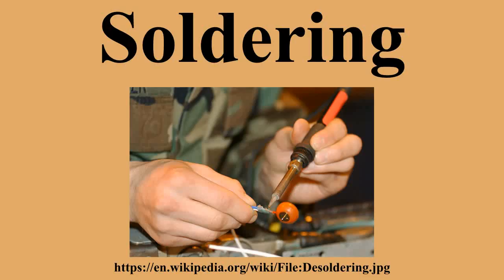These fluxes are called no-clean because the residue left after the solder operation is non-conductive and won't cause electrical shorts. Nevertheless, they leave a plainly visible white residue that resembles diluted bird droppings. No-clean flux residue is acceptable on all three classes of PCBs as defined by IPC 610, provided it does not inhibit visual inspection, access to test points, or have a wet, tacky or excessive residue that may spread onto other areas. Connector mating surfaces must also be free of flux residue. Fingerprints in no-clean residue is a Class 3 defect.